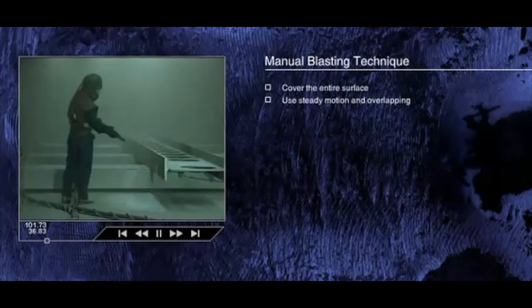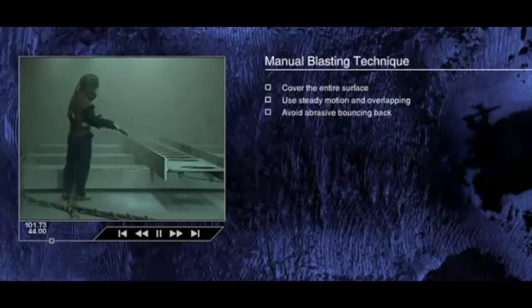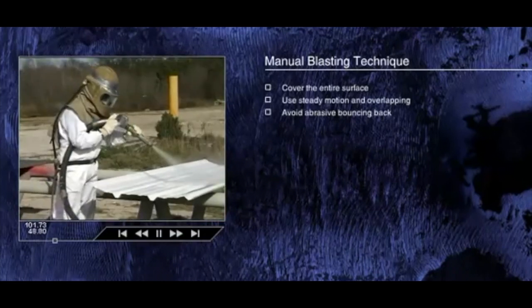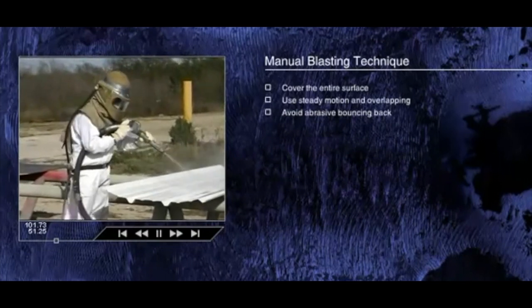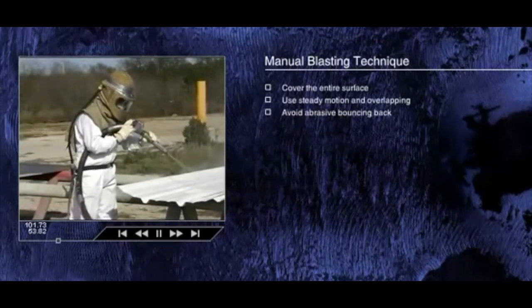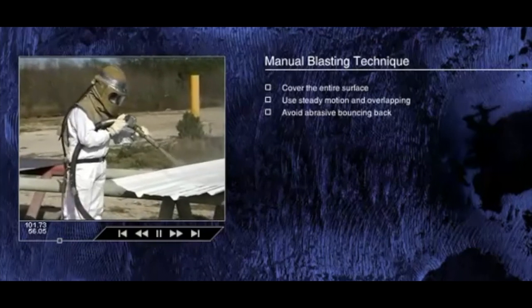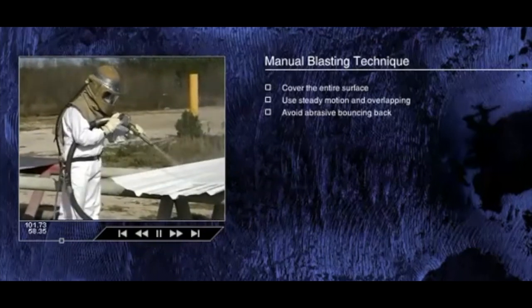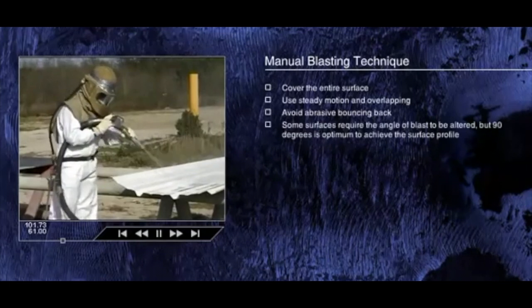The standard of blast cleaning should be no more and certainly no less than is required by the specification. The nozzle should be held close to right angles to the surface, but at a slight angle so that the abrasive does not bounce right back at the operator. Some surfaces, such as those with heavy mill-scale layers or with coatings such as thermal sprayed zinc or aluminium, are best blasted initially at a shallower angle, for example 45 degrees.